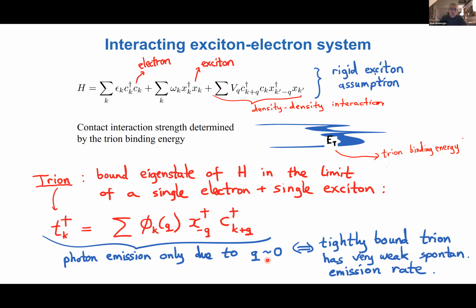Now, what that means for optical studies is this: if you look at this expression for the trion operator, and if you recall what I mentioned, that the exciton, when it decays and is converted into a photon, momentum conservation requires that its momentum has to be less than the photon momentum. That means that only a very small fraction of the excitons in this expansion are allowed to decay. So a very tightly bound trion has a very weak oscillator strength, because the amplitude for the q equals 0 state is going to be correspondingly small.